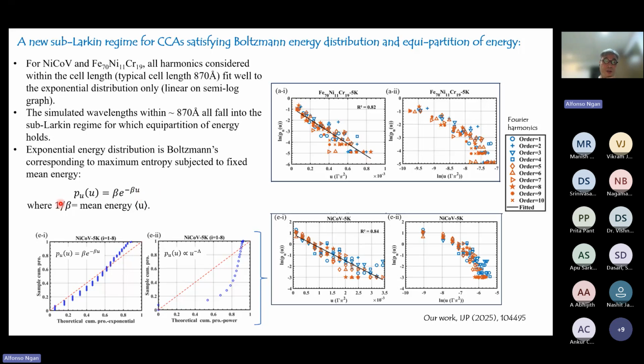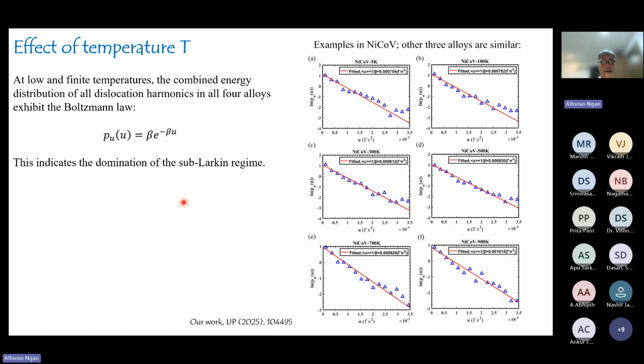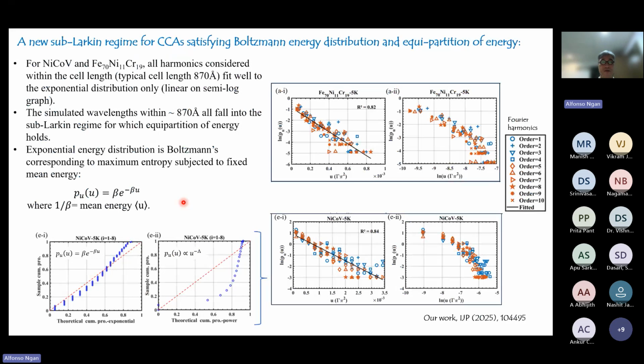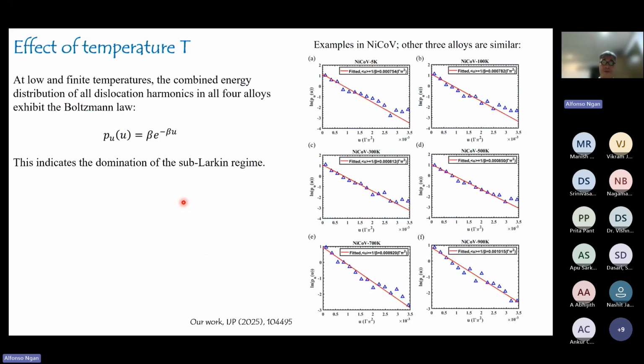All right, so we are seeing a new distribution not observed in dilute alloys, which is the Boltzmann distribution. This distribution corresponds to a linear plot in the semi-log. And we know that this corresponds to maximum entropy for a fixed mean energy. The Boltzmann distribution is based on the fact that if you maximize the entropy while keeping the mean energy, which is 1 over beta, constant, then the distribution of the energy should obey this law. Those simulations were carried out at 5 Kelvin, so very low temperature. If we repeat the analysis using higher temperatures, again, for every alloy, we are only seeing the Boltzmann distribution.